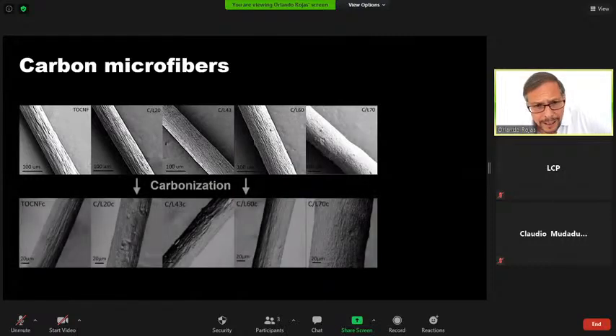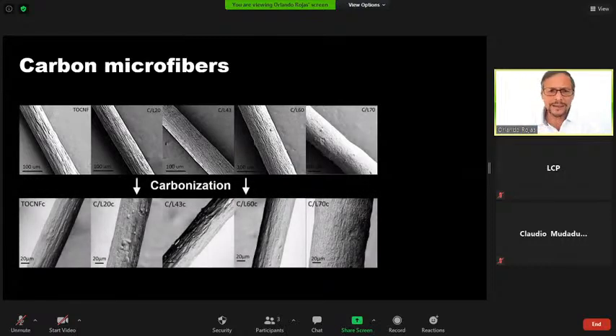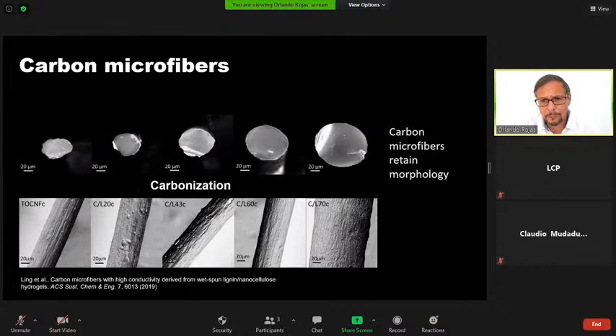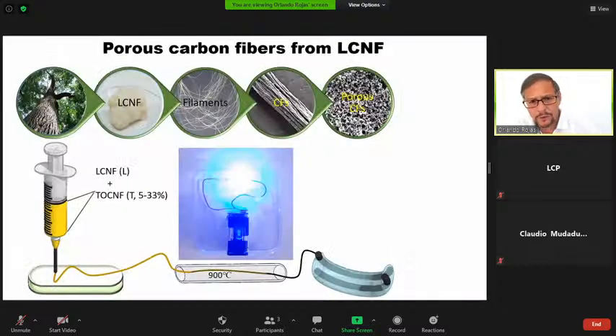And then those can be carbonized. And why do this? Of course, the idea here is that lignin has a very high carbon yield, and that means that we can produce carbon fibers quite easily. And these carbon fibers show very interesting properties, not only very good yield, but also the properties after carbonization of these microfibers are such that they are mesoporous, and that means that they can be ideally suited to produce electroactivity. So the case that I want to refer to here is these porous filaments that are highly conductive, as this process shows, and are also capacitive.